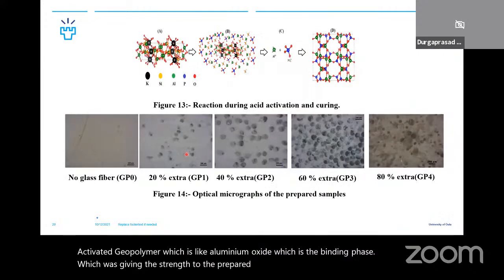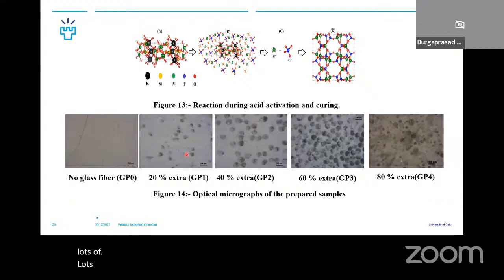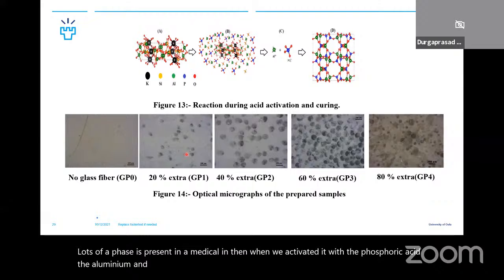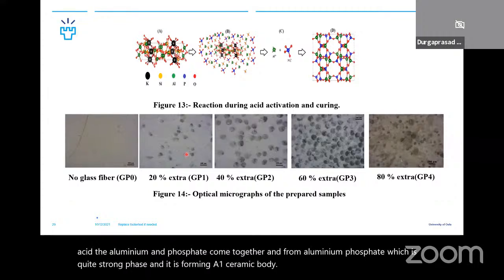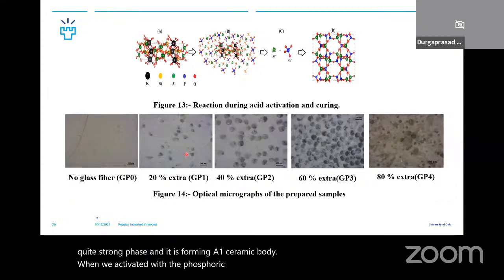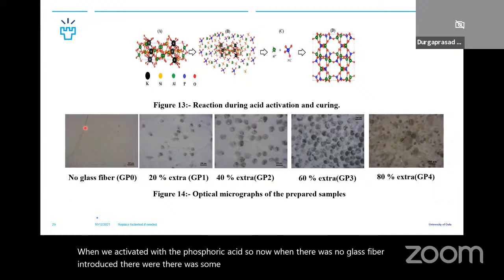So now the basic idea is that we have lots of phases present in the metakaolin. Then when we activated it with the phosphoric acid, the aluminum and phosphate come together and form aluminum phosphate, which is a quite strong phase, and it is forming a ceramic body when we activate with the phosphoric acid. So now, when no glass fiber was introduced, there were some micro cracks in the body we prepared.